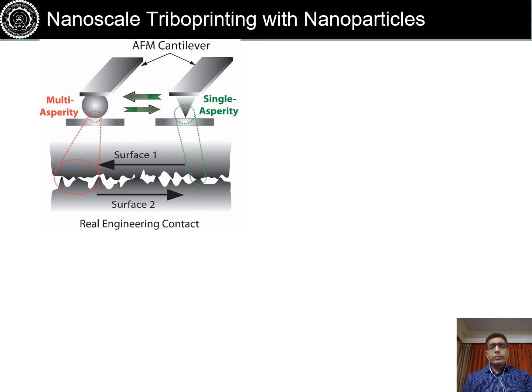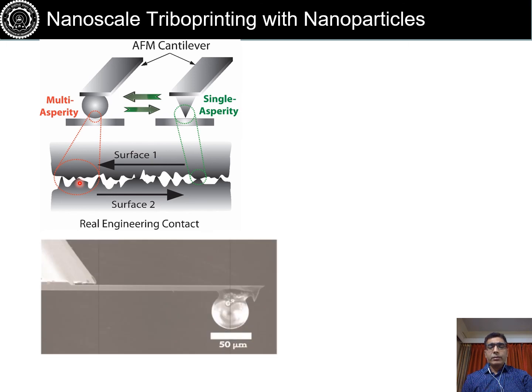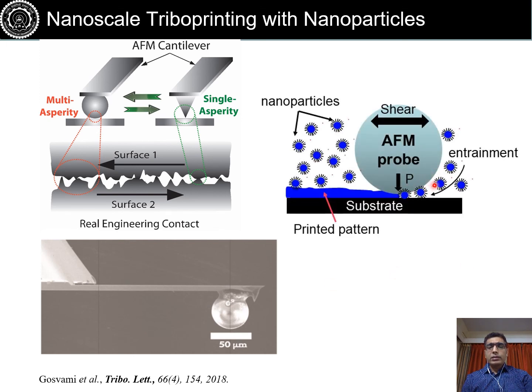Then we try to extend this to other species such as nanoparticles, and we realize that with single asperity it's very hard to trap nanoparticles at the interface, because nanoparticles are of the same size as the size of the contact in a sharp tip. So we took again this approach of using a microsphere, and with a microsphere now you have a large contact area, and if you have few nanometer size particles, you can easily trap multiple nanoparticles and probably write patterns, and that's exactly what we did. This is one such cantilever used in this work, and the idea is to trap multiple nanoparticles, and then under high contact pressure and shear you can deposit certain patterns.